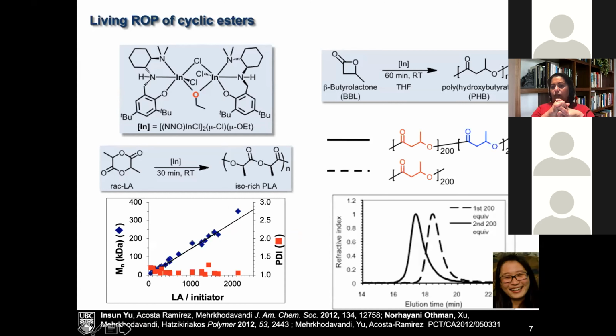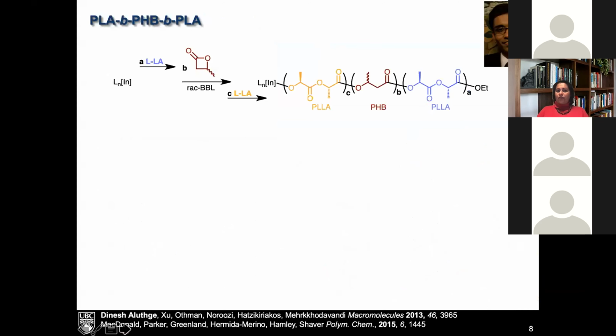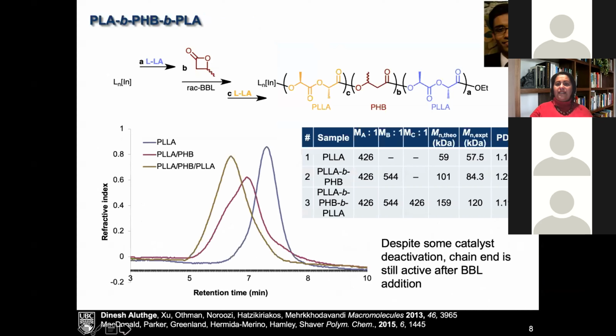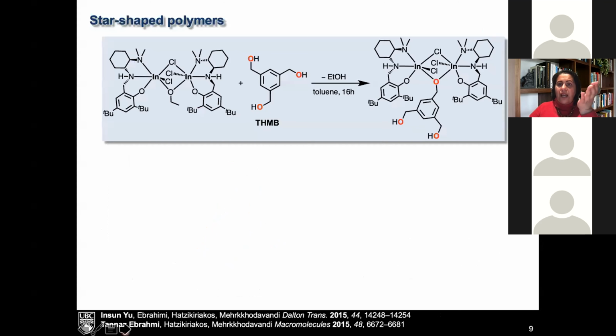And for all of these cyclic esters, what we can do are block copolymerization reactions, where you add your first equivalent of monomer, and that's the first one here. You can see that it's a beautiful monomodal, very highly controllable polymer. Then we can add another 200 equivalents of monomer and see this beautiful shift of the polymer to the higher molecular weight that you expect. You see that when you do lactide or butyrolactone or caprolactone or different cyclic esters, but you also see that when you mix them. So when you start from lactide, you add butyrolactone, you go to lactide, and you see the same behavior, where you start looking at higher and higher molecular weight. And this is also some of the early work that Dinesh did in my group. So it's a really highly controlled system.